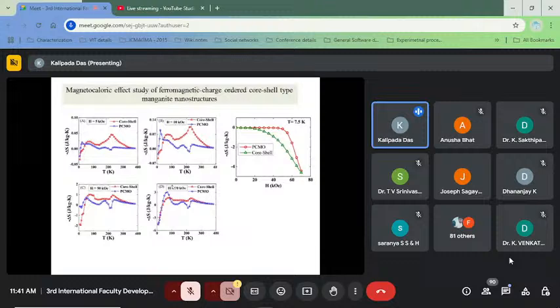But technologically, at a lower field value, if we get a larger value of the magnetocaloric effect, that will be more beneficial. That's why we have plotted minus delta S, that is the magnetocaloric entropy change, with respect to magnetic field change. And we see that in the case of the core-shell sample, we get a gradual change and a larger value with respect to the PCMO nanoparticle up to 50 kilo-oersted, that means a 5 Tesla magnetic field.